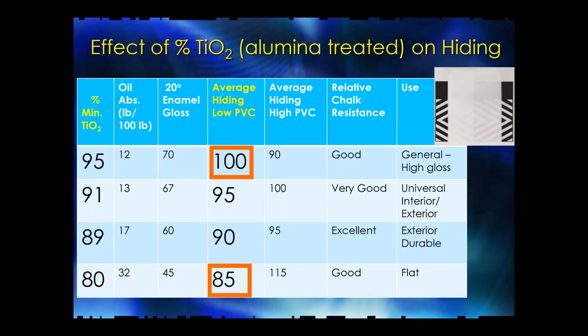Going down to the bottom, you can see that you can buy titanium dioxide that is 80% content. And why would you want to do that? Well, that has a fluffy silica on the surface. And the problem is that the more of the other materials that you put on the surface, the thicker the silica coating, the worse you'll get in terms of hiding power. In a very crowded system, it's good to have some of this coating on the surface. So we have to consider whether we are in a low PVC, pigment volume concentration, system or a high PVC concentrated system. Up on the right, you can see the difference between a 100 and an 85. So we're talking about, and of course, hiding power is dependent upon coating thickness.